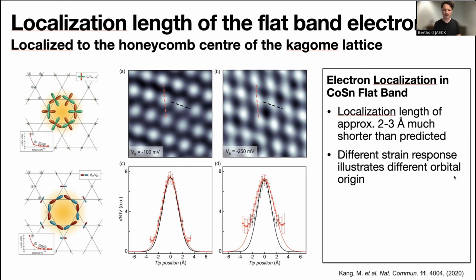Yeah, we also find, and I think this is a detail, but perhaps worth noting, that when you look at the 2 different flatbands, one residing at slightly higher energy, the other one at slightly lower energy, they exhibit a little bit different response to the about 2% tensile strain that we find in our cobalt tin thin film. And while this is a little bit of a detail, it sort of illustrates that both these states probably derive from different flat band orbital states.